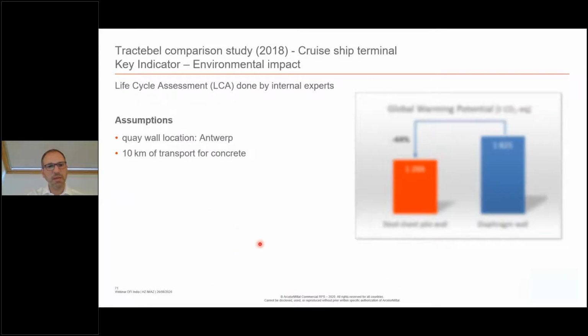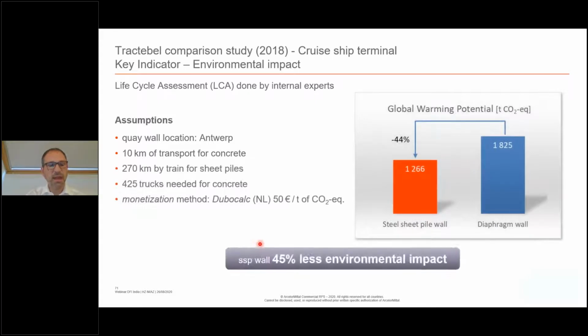And from a life cycle assessment, which is also very important because in fact we want to reduce the environmental impact, we analyzed an indicator which is a CO2 equivalent, and in this case, under those assumptions, the sheet pile wall has a 45% lower environmental impact. But of course, this applies only to this specific project and under those conditions.